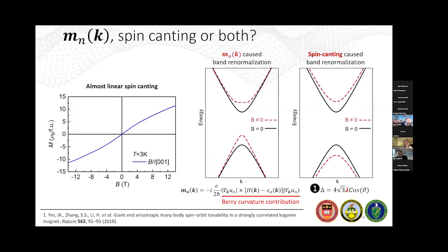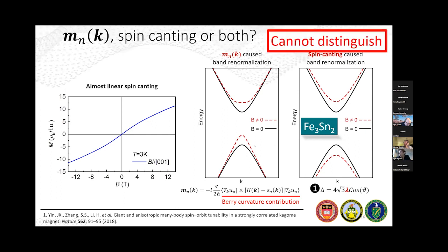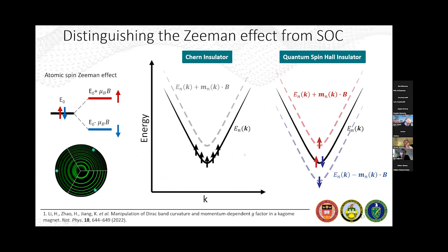To look at the explanation for this, we explored two different scenarios. One is related to the orbital magnetic moments related to the Berry curvature. The other is something that was proposed in a reference, where due to spin-orbit coupling and tilting of the spins, you essentially round up the Dirac cone by increasing the Dirac gap. In this system, which is a helical antiferromagnet, if you measure the magnetization as a function of applied magnetic field, you essentially just get spin tilting. So in this system, we cannot distinguish these two scenarios, which is why we turned to the second system.